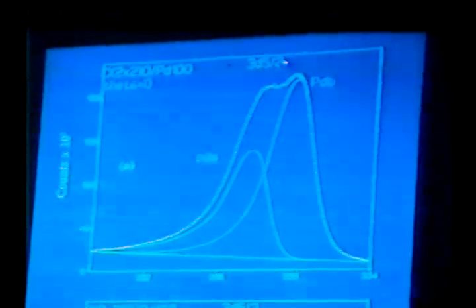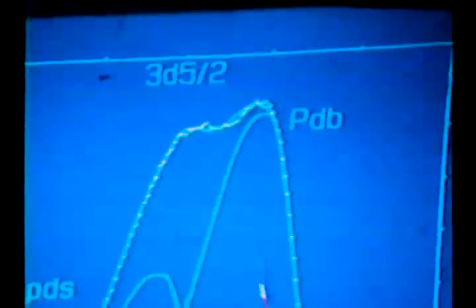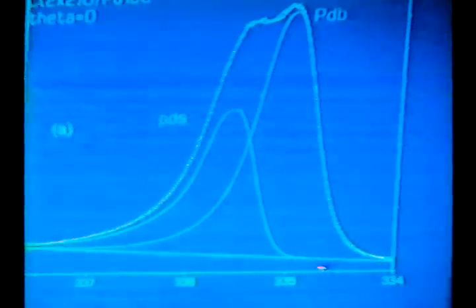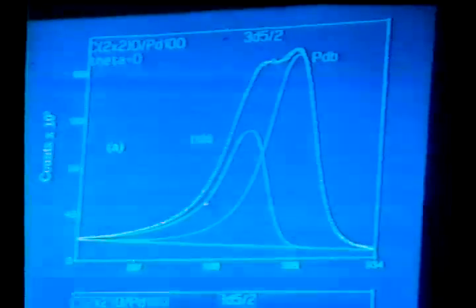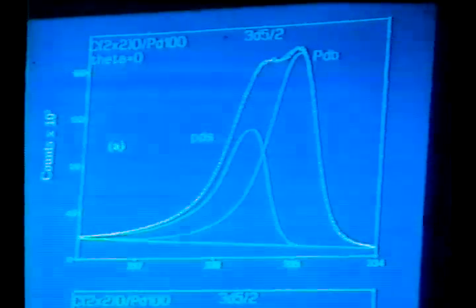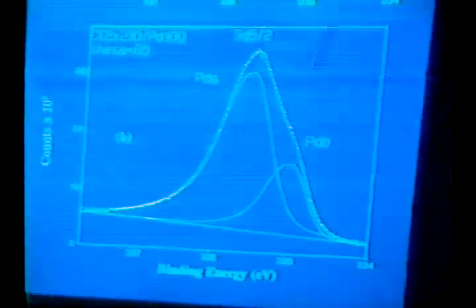This is a palladium (100) face. These face-centered cubic lattices, which is the (100) face, are just about the only ones that do not relax significantly. We have chosen this plane for analyzing oxygen chemisorption in some detail. The oxygen structures have been well characterized, and we've looked at the half monolayer c(2x2) structure in core level emission